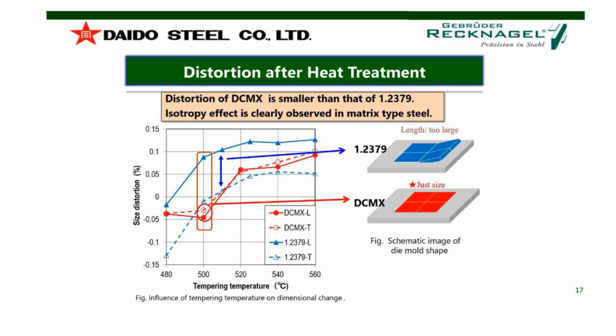the blue lines for D2 grade. The filled triangle is for the distortion in length direction of D2 grade, and the empty triangle is the line for the distortion in thickness direction and width direction. And as you can see, you have always a big gap between the length distortion compared to the thickness distortion. If you use a temperature of about 480 degrees, or if you use a higher tempering temperature, it's always a big gap between length and thickness.